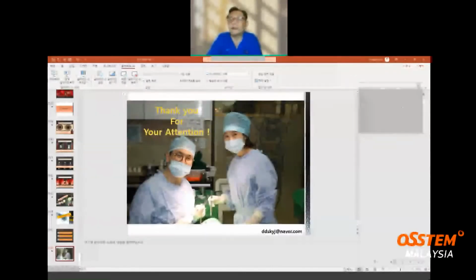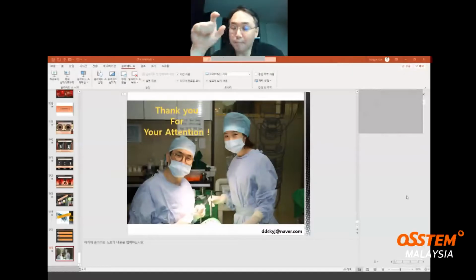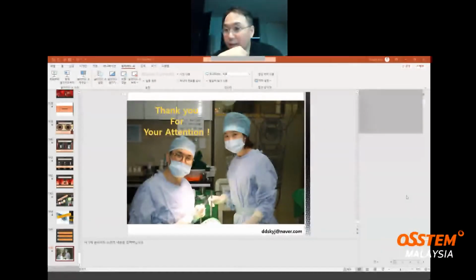Yeah. The next question is, since the nano-hydroxyapatite layer or the coating is thin, is there a worry about the surface coating damage or peel off during implant insertion? Surface damage. Yeah, but the particle size is quite small. Nano size hydroxyapatite particle was coated on the NH implant. Even though the insertion torque is greater than 15 Newton centimeter, there was no delamination.